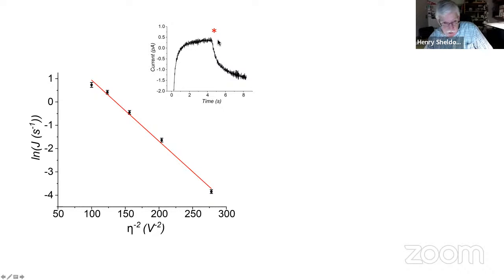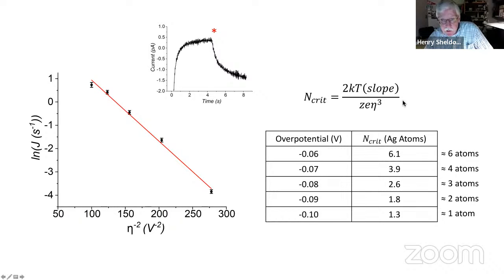So what do you do with that? Well, without getting into the theory or all the math, there's a very simple expression that you can derive, where you can compute the number of atoms in that critical radius, n is the number of atoms, from the slope of this line. And the equation has kT in it. We know those numbers. It's got the charge of the ion, silver +1, the charge of an electron, and it's got the overpotential raised to the 3rd power.